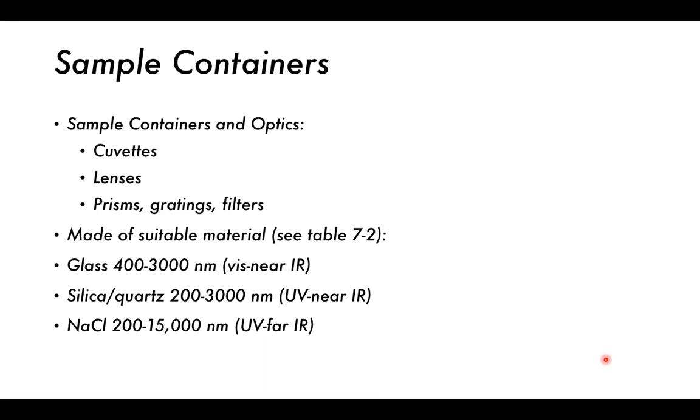And then sodium chloride is by far the best, has the widest range. But as we've talked before, it's not suitable for aqueous samples. It cannot be used in high humidity environments. It's difficult to handle. You can't really touch it with your fingers. It's very delicate, but it is very, very powerful as a tool for measuring organic samples or anything really that won't interact with the sodium chloride.